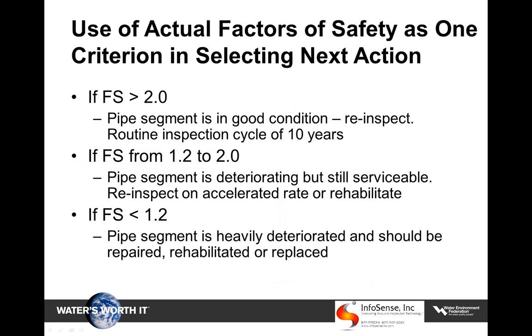With this client, we came up with this category. If the factor of safety that we calculated under actual conditions was greater than 2, which is a standard design factor of safety, then the pipe segment was in good condition, and we only needed to re-inspect, perhaps on a routine inspection cycle. If it was less than 2, but greater than 1.2, we determined the pipe was deteriorating, but still serviceable, depending upon where in that range it fell. And we can either re-inspect at an accelerated rate, say in 5 years, or if it's very close to 1.2, or if it's got a lot of holes or pits in it, then we may decide to repair or rehabilitate it now.